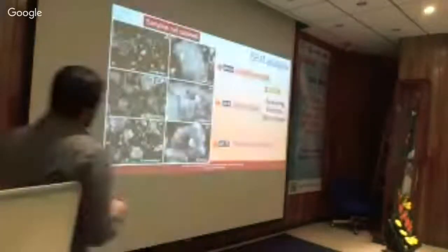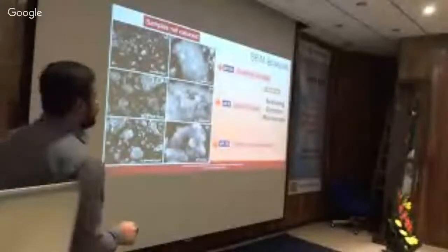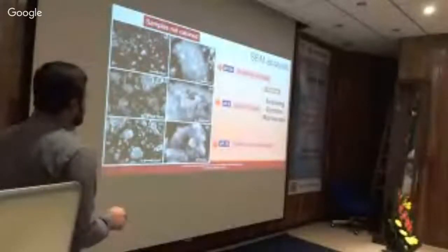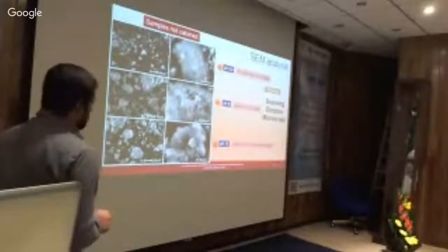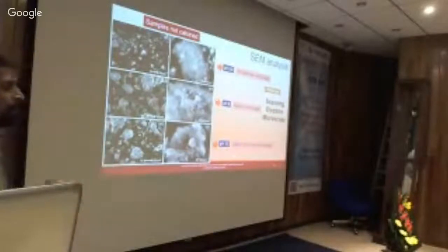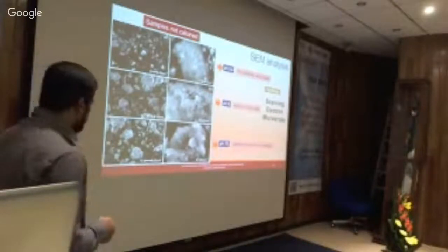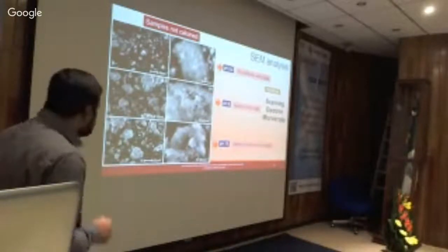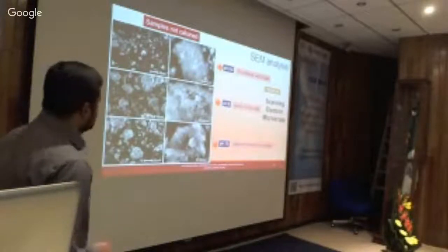Hydroxyapatite powders before calcination: you can see all around 5 to 40 micrometers, and we can see the addition of nitric acid. It makes some porous structures, but really they are totally agglomerated because they are not calcined. So there are a lot of residues on the surface, which agglomerate and form larger grains, and there is not much difference in grain size between the pH values.